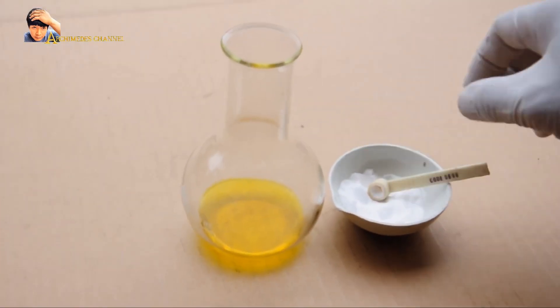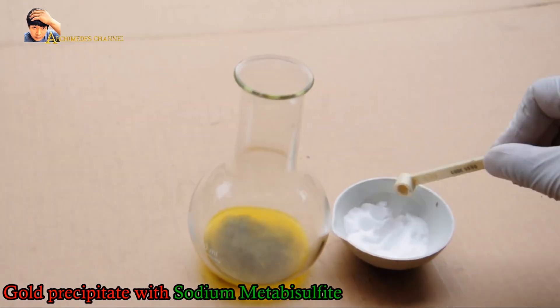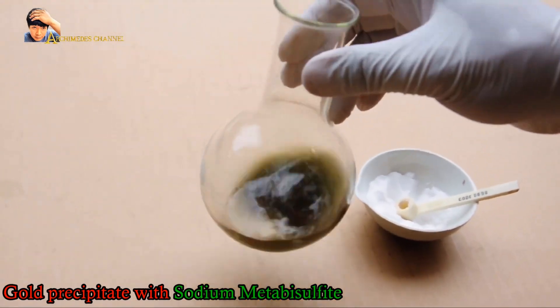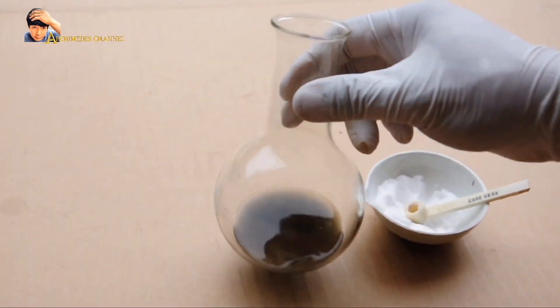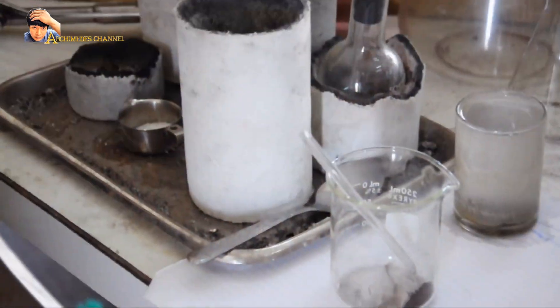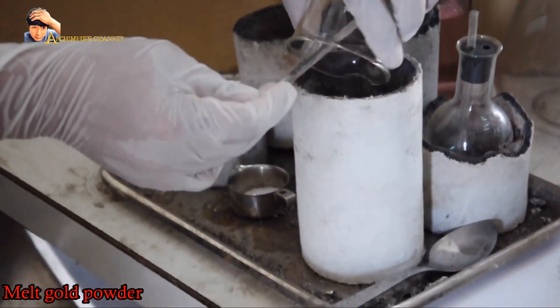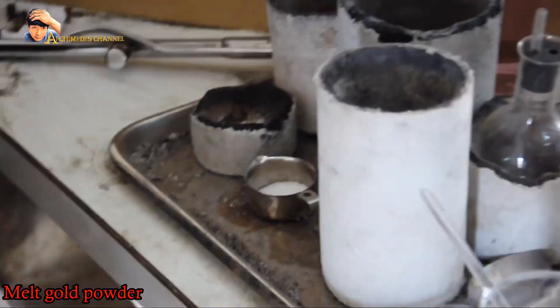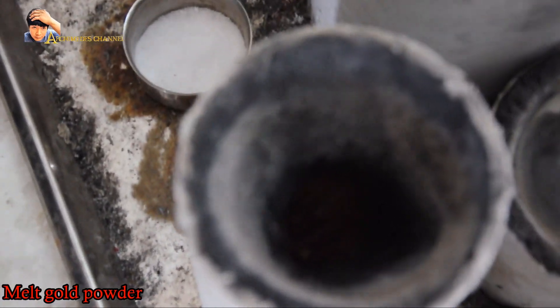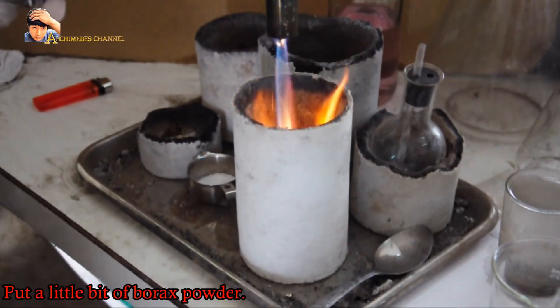Using sodium metabisulfite, the gold can be made to settle as sediment at the bottom of the aqua regia solution by slowly adding sodium metabisulfite until reaching saturation level. The recovered gold can then be sold to a gold buyer or kept for personal use. Its value will depend on its purity and the current market price of gold.